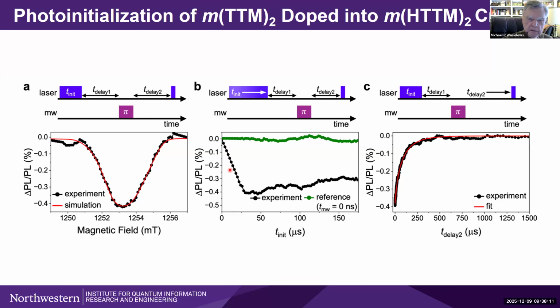But there is a bit of a delay on the way in, and you see this straight line. This is not data, this is the limitation of the resolution here. You can see this lasts a long, long time. And how long does this last? Well, we can do this experiment the other way and look at the decay of the effect. It's decaying in something on the order of 120, 130 microseconds in this particular case. So it's behaving itself quite nicely in the crystal.